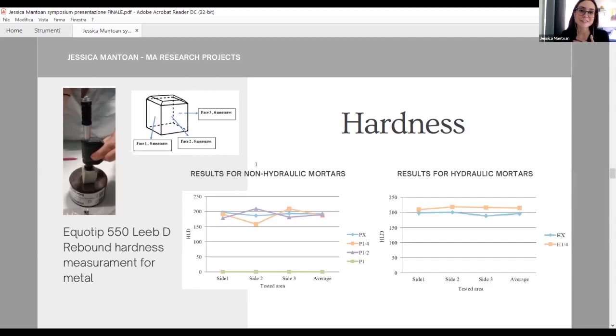As you can see from the result, for non-hydraulic mortar, mortar containing small and medium amounts of barium hydroxide additive present a quite similar hardness with respect to the control sample. We can see a kind of deviation, but generally speaking, the average of the hardness results is mostly the same. Completely different results show for the sample P1, containing a really large quantity of barium hydroxide additive. It resulted so soft that it was under the unit measure of our equipment, because it was really, really soft.